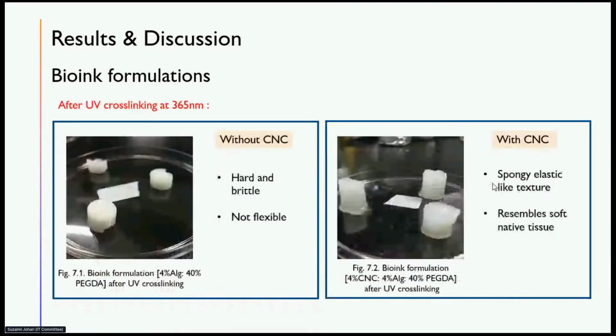Next slide. And then when they are subsequently UV cross-linked, they become firm and stable. At this stage, they are double network bioinks. So you can actually pick this up and then they will not be destroyed as compared to the single network bioinks. And an interesting observation is that the bioinks with CNC show the appearance of a flexible, spongy, elastic-like texture compared to the formulations without CNC, which show hard and brittle characteristics. This result suggests that the addition of CNC actually improved the appearance of the hydrogel, making them have a closer resemblance to the soft native tissue. Next slide.